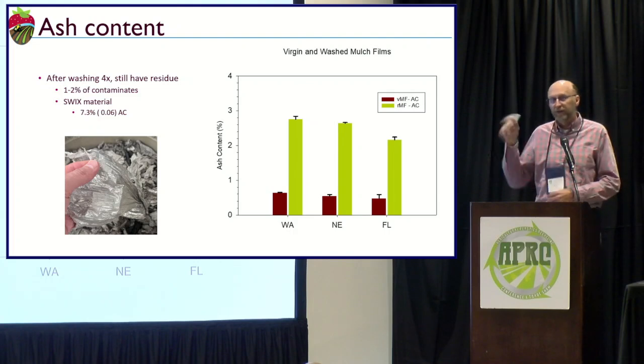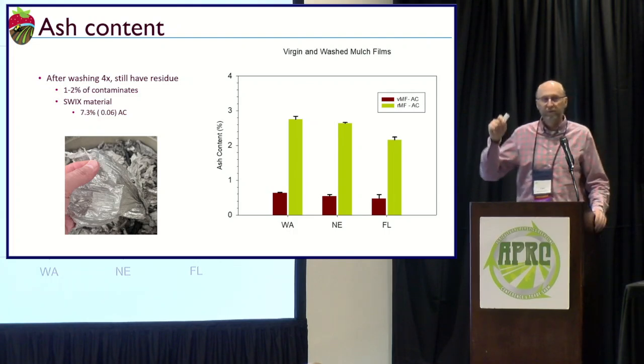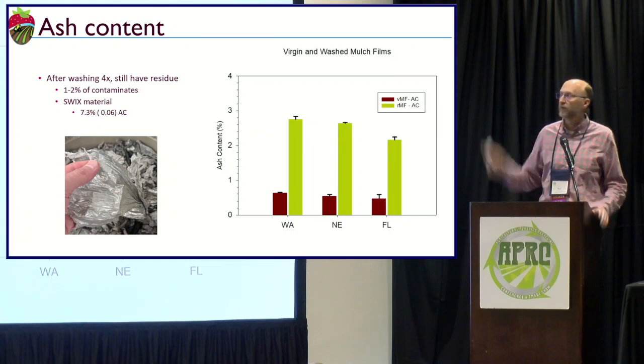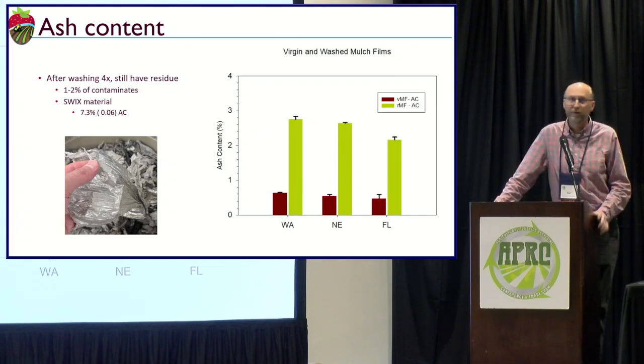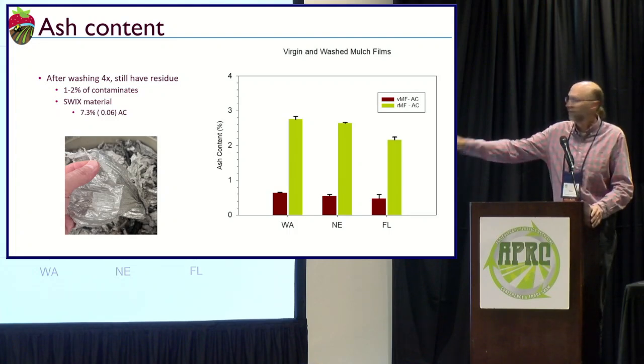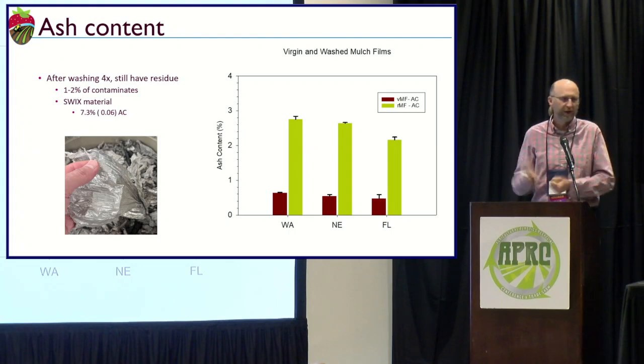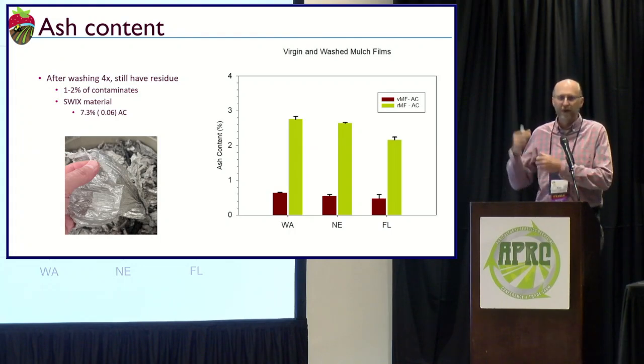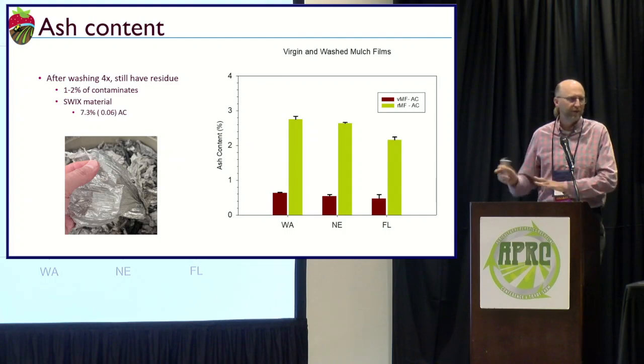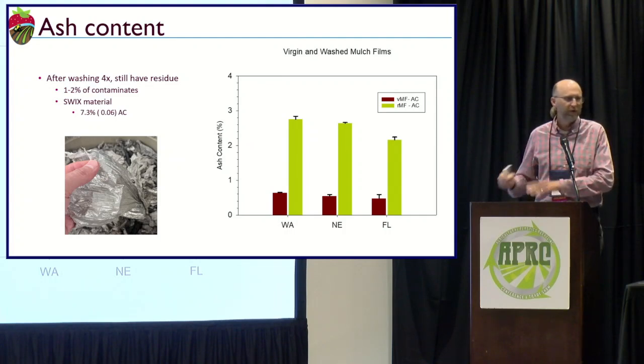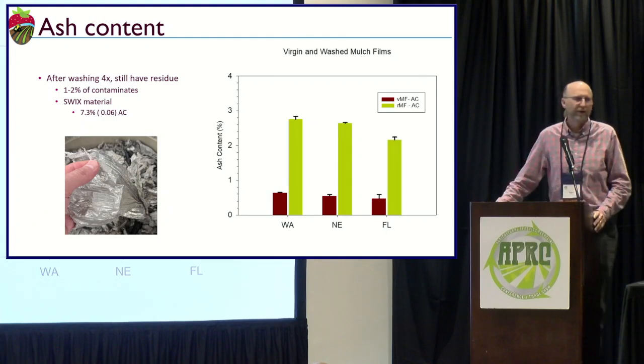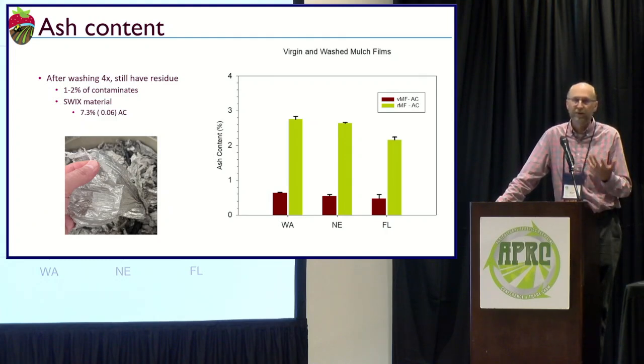So ash content, that's when you take the material that we've washed 4 times, and then we get the actual content of the inorganics in there. We run it at 600 degrees C for a couple hours, and then we end up with what we classify as an ash content. The red bars are a virgin mulch film. That's the mulch film that stayed in the box that we got, that was going to be put out on the field, but it didn't. It's never seen sunlight. It's never seen soil, so that's your virgin mulch. You're at about 0.5% ash content, which is about normal because that's your pigments. They may use a little calcium carbonate in there to extend the resin out, but that's about normal.